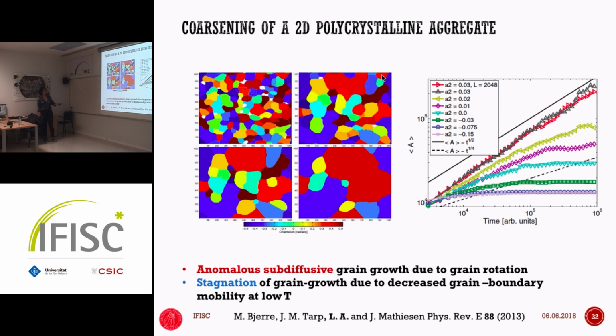In particular, for a bigger system, you can have a map of the grain orientation, and you can see that at the beginning you start with a lot of small grains, but when you let the system evolve, you eventually go into larger and larger grains. It's called the coarse-graining process. If you calculate the average area of the grain as a function of time, you see that it's growing with time. At low quenches, close to the critical point, you see normal growth, which is basically driven by the surface energy. But when you go to deeper quenches, you have this anomalous growth that is poorly understood, but it's observed in molecular dynamics simulations and in experiments. And there are various theories related to this slower coarsening behavior.